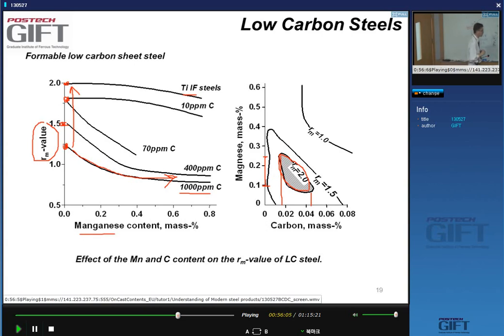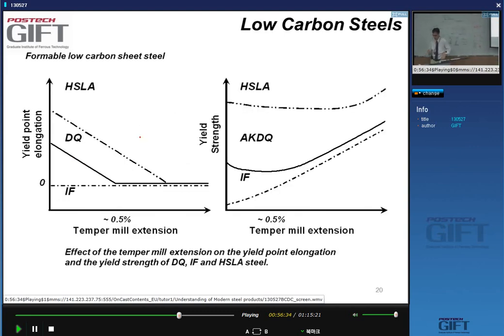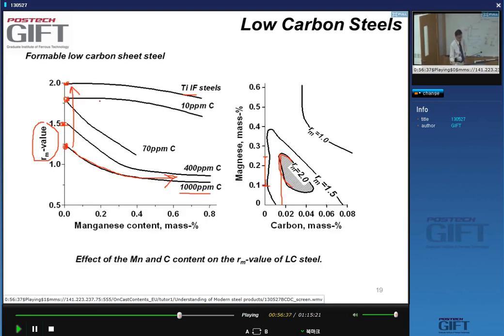That's also the reason why low carbon steels, we usually don't make them with lower than 200 ppm carbon contents. We could make them lower by, for instance, decarburizing more in the BOF. We don't. It doesn't pay off, right? Because of the presence of the manganese. Okay. And what's important here, for instance, is you will see that in the IF steels, where the carbon is stabilized as titanium carbide, the influence of the manganese on the R value is much, much lower.